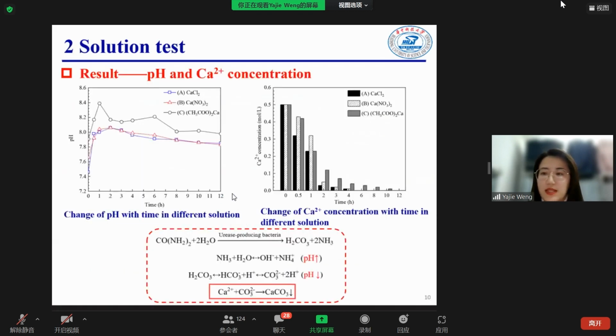The results show that for the 3 calcium sources, pH changes with time, first rising, then decreasing, and then stabilizing. According to the analysis of the MICP principle, carbonate and ammonia are generated after urea hydrolysis. The hydroxide ion leads to a rise in pH, and the hydrolysis of carbonate leads to a decrease in pH. The 2 ions combine to form calcium carbonate precipitate when the pH is stable.